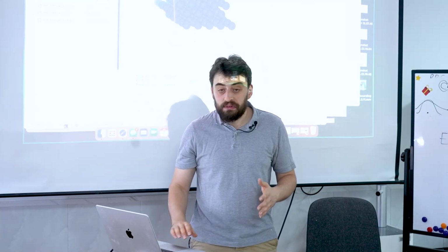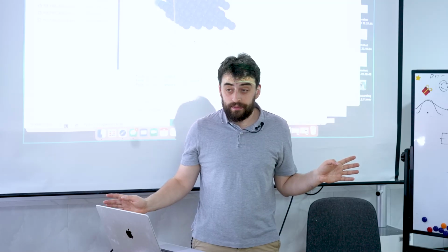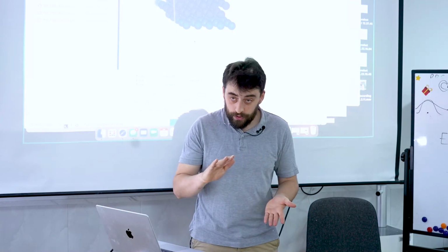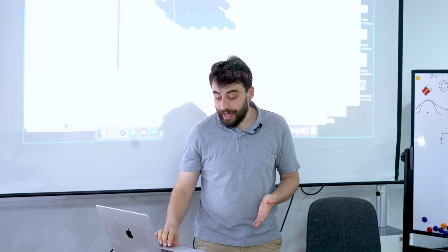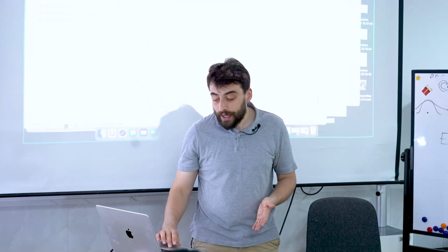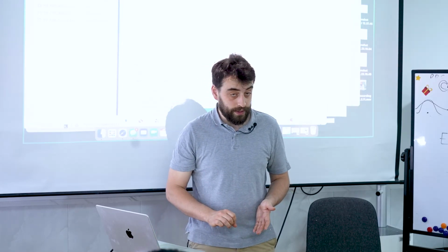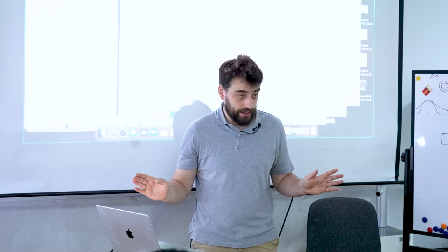In the Z direction, we don't care about that, because we don't have a crystal in the Z direction. We've broken the crystal symmetry. That means we can play a nice trick and say that in the Z direction we have gamma point symmetry. We get rid of our K point in the Z direction.